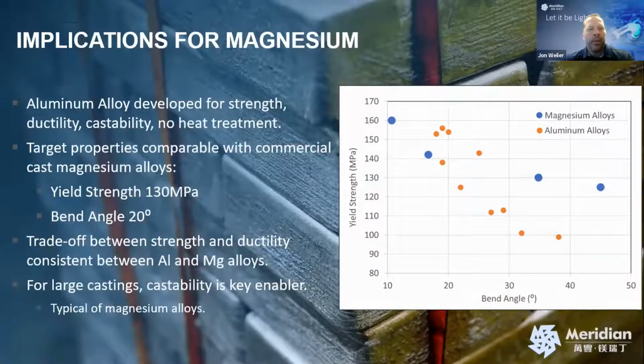And then the last one was the aluminum alloy. So again, the aluminum alloy was developed for strength, ductility, castability with no heat treatment. These target properties we're looking at, so yield strength of about 130 with good castability and no heat treatment. It's sounding a lot like a typical high pressure die cast magnesium alloy.